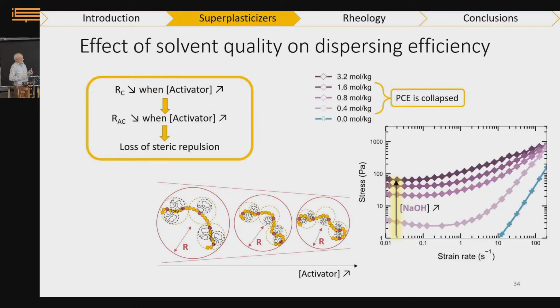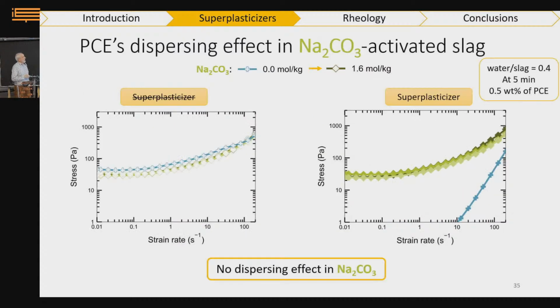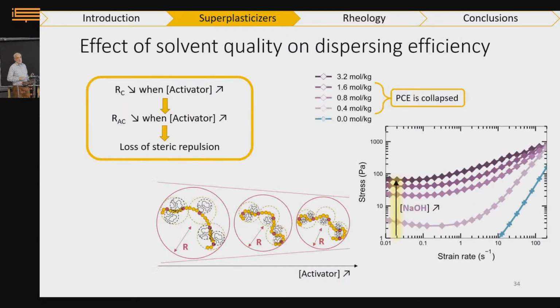We have no direct proof of it, but the correlation is striking, or if you want, seducing. So the story I want to tell is that as we add sodium hydroxide, progressively the coil shrinks and the steric effect is less and less pronounced, and therefore the yield stress increases. That is, the interaction between the grains comes back into the story. After a certain level, of course, you have salting out, so the polymer is not soluble anymore, and then it's as if there were no polymer soluble. So the story seems relatively simple in terms of sodium hydroxide.